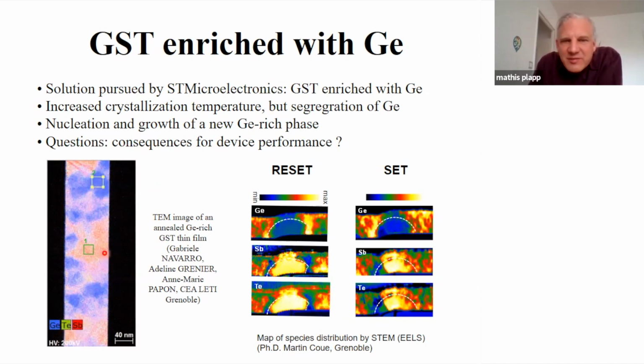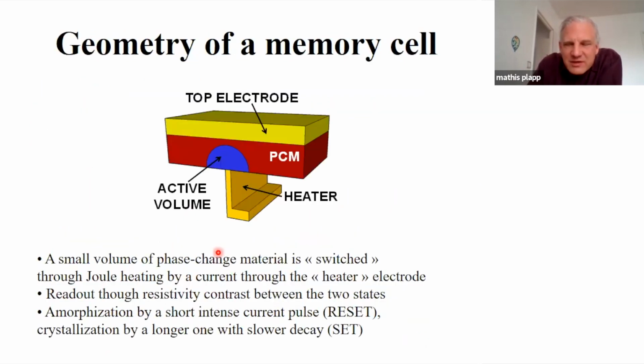And there are regions where germanium is almost absent, and these correspond to crystals of almost pure germanium with a little bit of dissolved tellurium and antimony, and the reddish region here corresponds to the classic GST. And so here to the right, you see a memory point. So you have to imagine this is this mushroom geometry that you see here, okay? So the material that is actually processed during the memory operation is this blue region here.